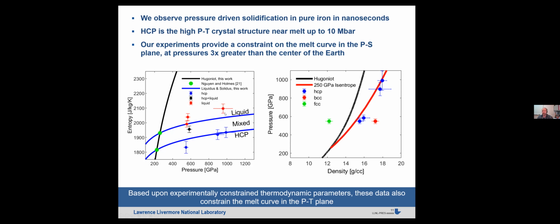The other one was a question about the stress state. To obtain the stresses, we did a forward optimization to the interface velocity between the iron and the lithium fluoride, where we used hydrostatic equations of state for lithium fluoride and iron. These hydrostatic equations of state were benchmarked against NIF ramp compression data obtained by Ray Smith. And so I would say this is a point where the expected shear stress may affect the peak pressure state at the level of a few GPa, maybe up to 10 GPa, which is still within the systematic error bars here. Not very significant.